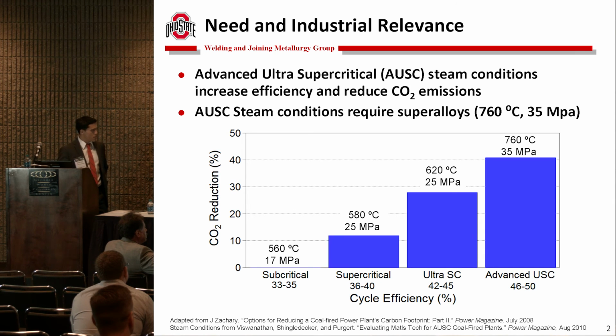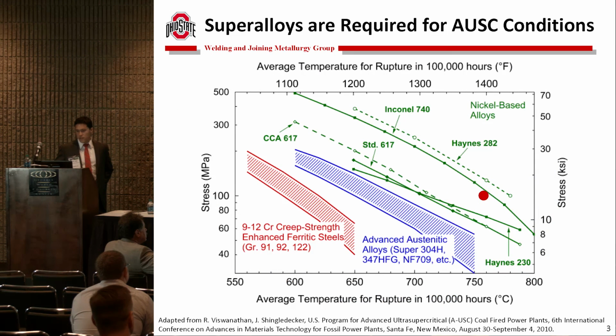The critical term here has to do with the critical point of water when you get to a supercritical fluid. Anyway, the material conditions desired for AUSC applications are a rupture life of 100,000 hours at 760 C and 100 MPa. When you put this point on here, you see you've pretty much narrowed it down to only precipitation strengthened nickel-based alloys. The two leading candidates are alloy 740 and alloy 282. Alloy 282 actually wasn't designed for this application. 740 was, and so it has advantages in terms of fireside corrosion resistance.